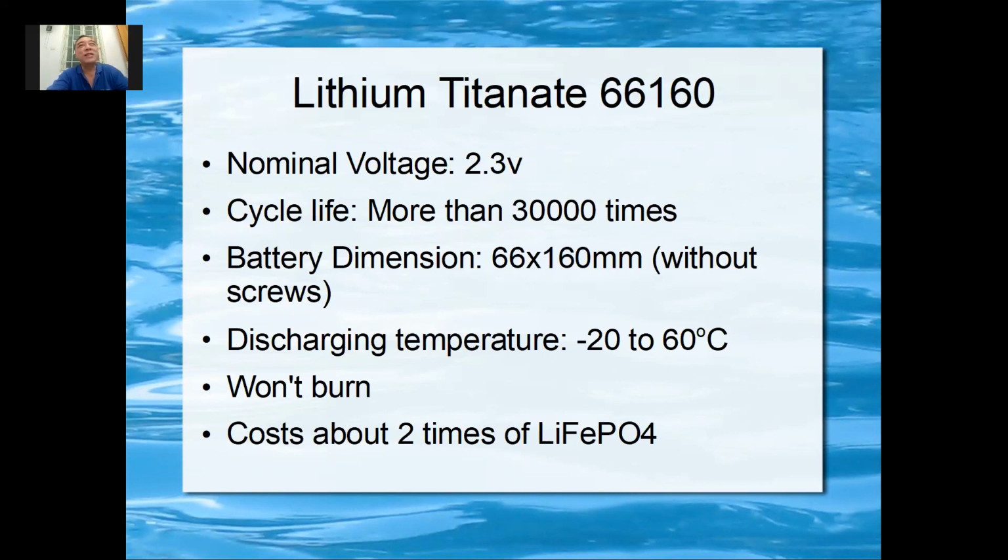And the best thing is when they count how many times you can charge and discharge, they only charge and discharge 20%. That means it's only 80% charge. They charge up to 100%, and then they discharge to 80%, then they charge again, then discharge. They don't discharge fully, and then they do that, okay, 1,000 times. They assume that you don't use until flat.